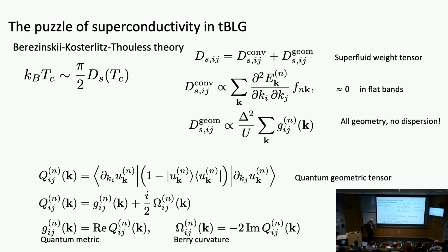In other words, the nature of the electronic states, u_k, changes as a function of k as you go through k values in the reciprocal space. And this change cannot be trivial, because if it's trivial, it doesn't give any contribution here. It has to be a non-trivial change as you change the momentum index of the electronic states in the system. That's the essence of this, as best as I can describe it in words, not with fancy formulas. And I'll come back and try to illustrate this in our case.